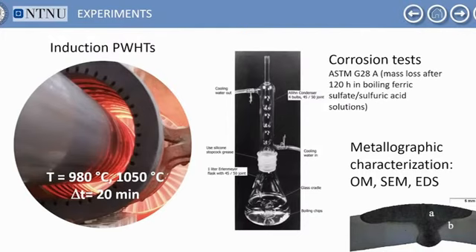We perform also corrosion tests according to ASTM G28, method A, and then we carry out metallographic investigation in the three most important zones of the joints, the fusion zone, the heat affected zone, and the parent metal, using optical microscope and scanning electron microscope with EDS in order to investigate the redistribution of the key elements in the welded joints.